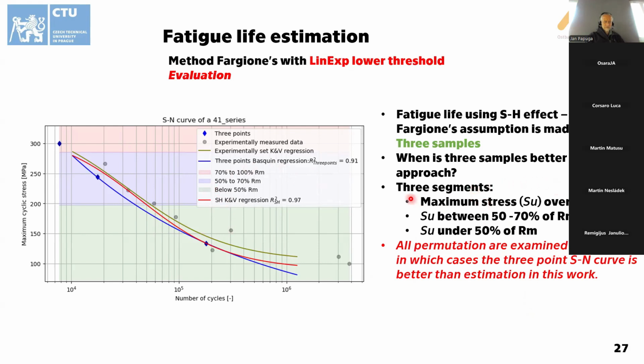One is based on the maximal stress. One segment is over 70% of ultimate tensile strength. One is between 50 and 70% of ultimate tensile strength, and one which is related to the fatigue limit, or let's say higher fatigue life, which is under 50% of ultimate tensile strength. All these permutations, taking 1 point here, 1 point here, and 1 point here, make a Basquin regression out of it, which is compared to the one that was produced by the methodology presented prior.